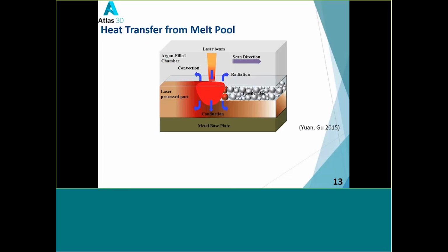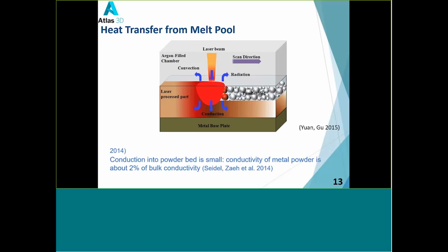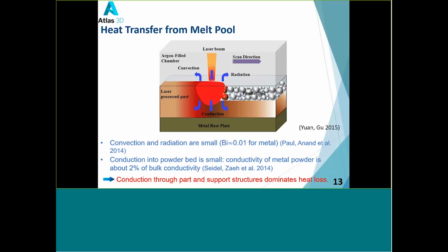And the heat transfer you see here is that when we melt the metal powders with the laser beam, heat will conduct from the melt pool region to the other part of the part. And the heat also will transfer to the chamber through convection and also through radiation. And we found that convection and radiation are small in comparison to the conduction. This is especially true for metal. And the conduction into the powder bed is also small because the conductivity of the metal powders is about only 2% of the bulk conductivity. So actually, most of heat just conducts through the part and support during the AM build process.